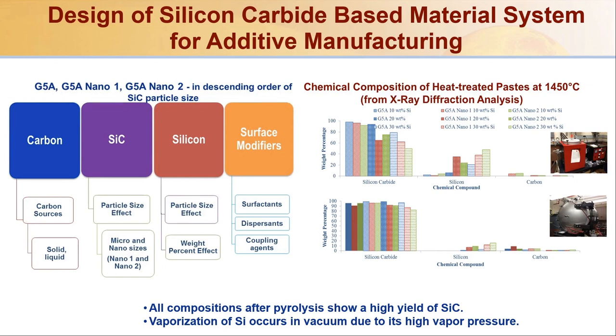So we do heat treat these things up to 1450 degrees C, which is typically the temperature you really need to convert silicon and carbon to silicon carbide, and that's a typical temperature used for even silicon infiltration as well. We do see some vaporization of silicon in the vacuum due to its high vapor pressure as well.